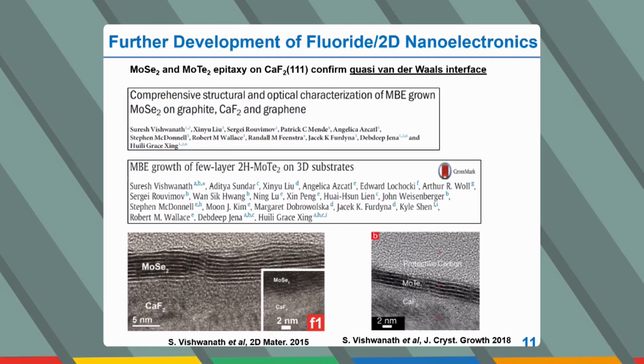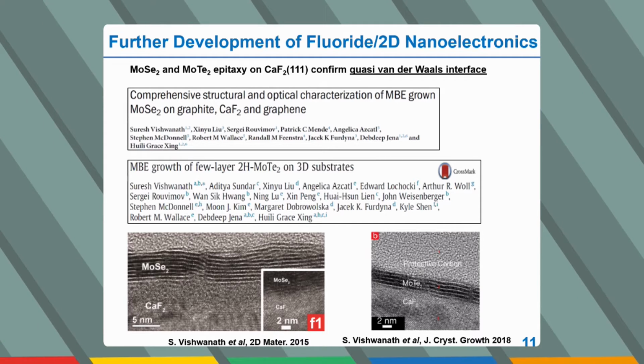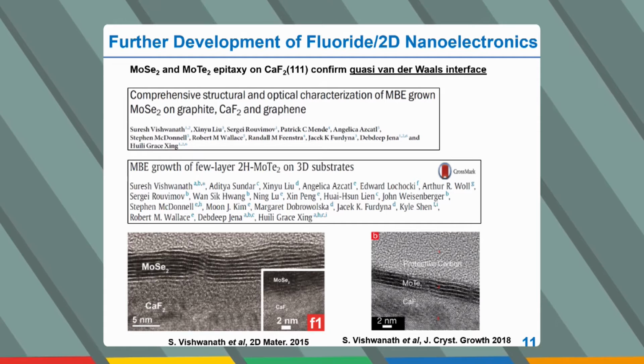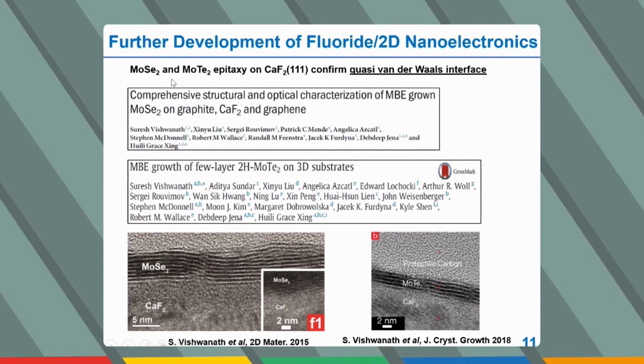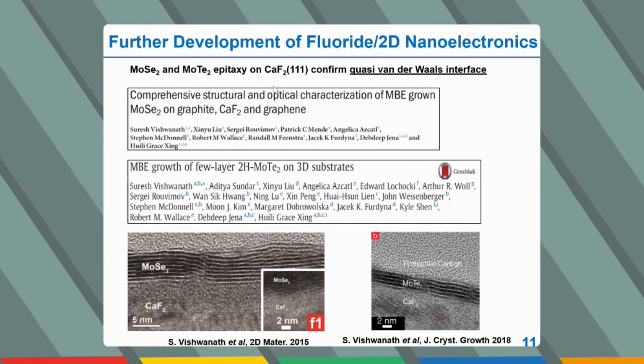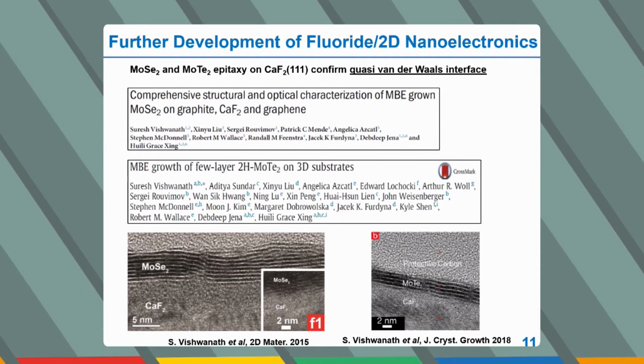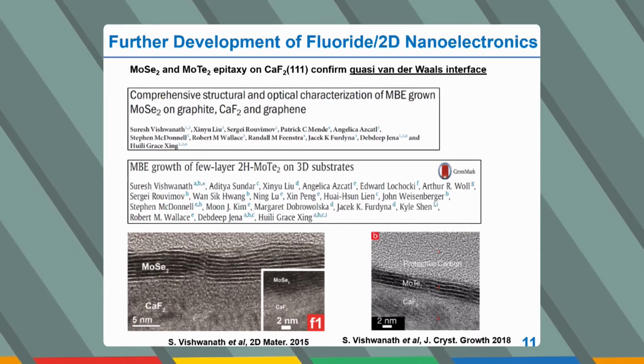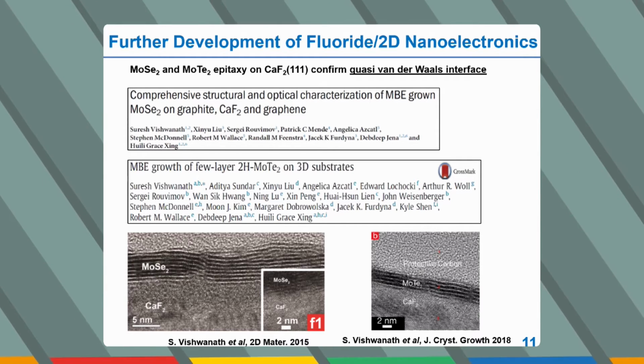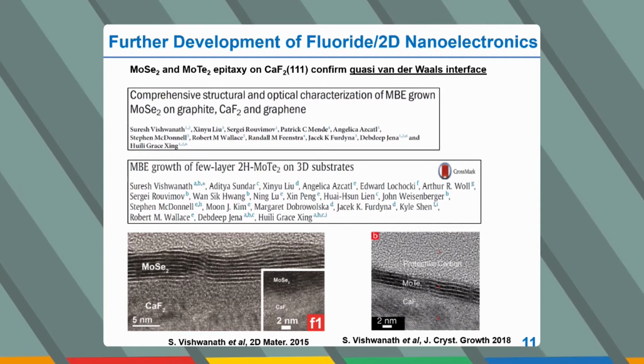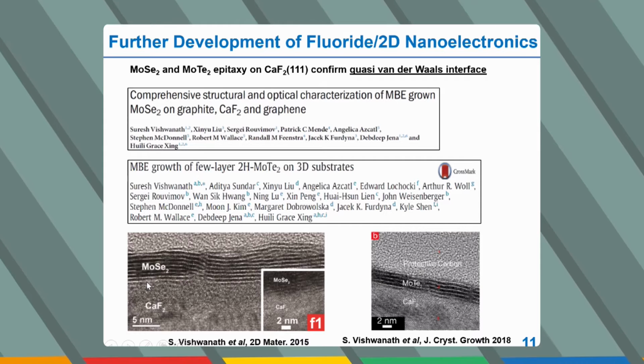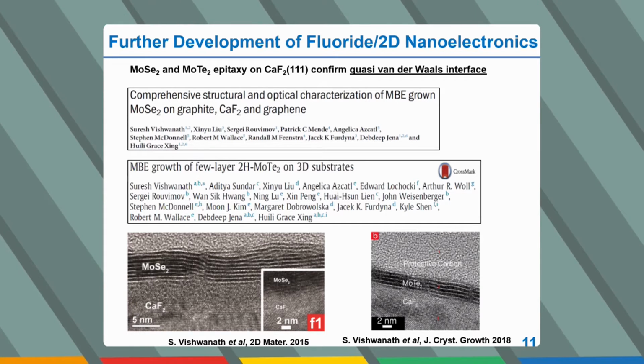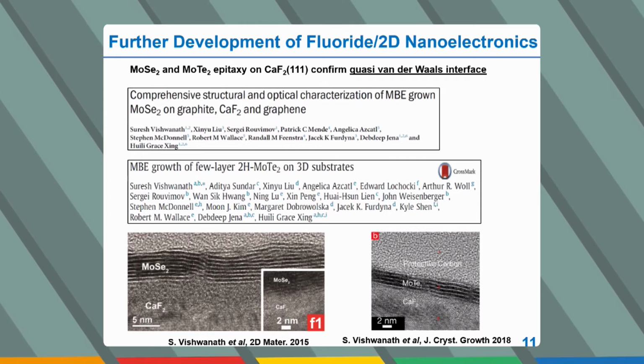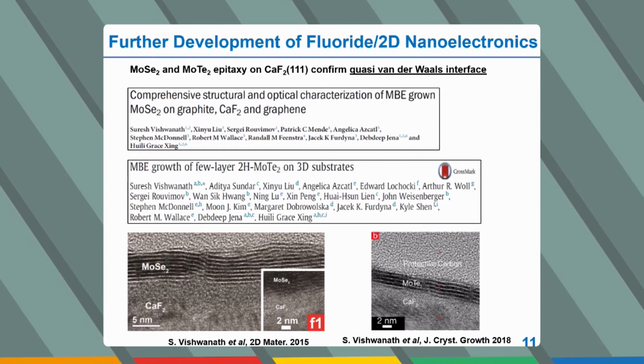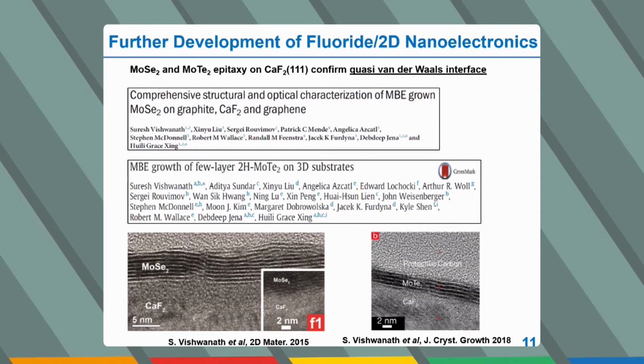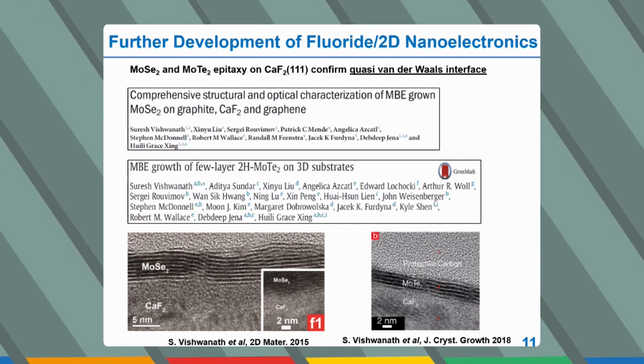So we achieved the first success in integration of calcium fluoride into the technologies. But actually, previously it has been shown that such TMDs like MoS2 can be epitaxially grown on calcium fluoride, while we use just transferred CVD grown films of MoS2, and our MoS2 films were grown on sapphire substrates. And this means basically that calcium fluoride can be fully matched with 2D technological process flow, and in future we can grow 2D channels directly on top of calcium fluoride, and probably calcium fluoride on top of 2D channels to go to top-gated devices, which will be required for circuit integration.